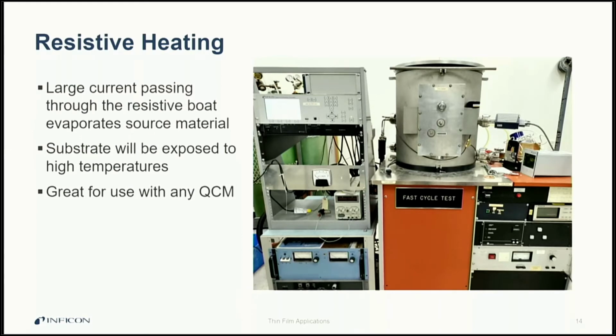So the first method for depositing a thin film would be using resistive heating. In resistive heating, we pass a large current through a vessel containing a source material that is in a solid state. The vessel could be what's referred to as a boat, but it also could be a crucible or something as simple as a wire. And as the vessel heats up, the material in the boat eventually changes phase from a solid to a gas. The gas then coats the cooled surfaces in the chamber, such as the substrate, QCM sensor, and the chamber walls to form a thin film.